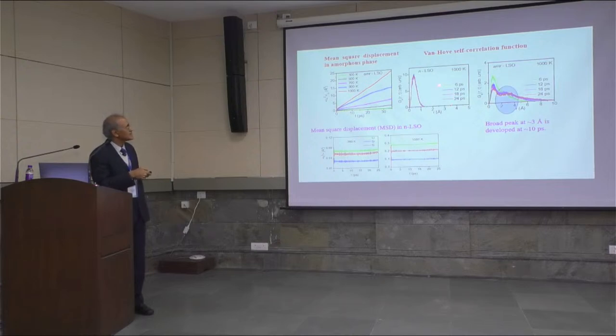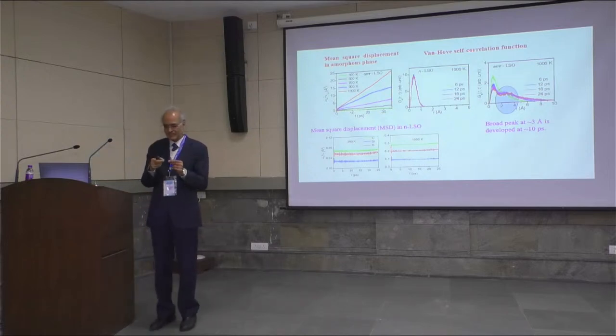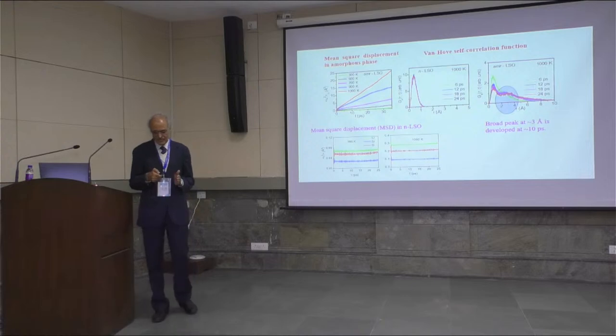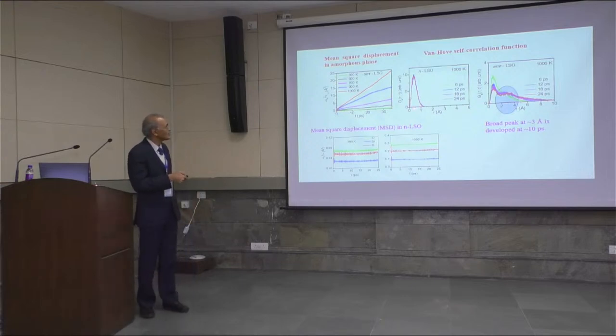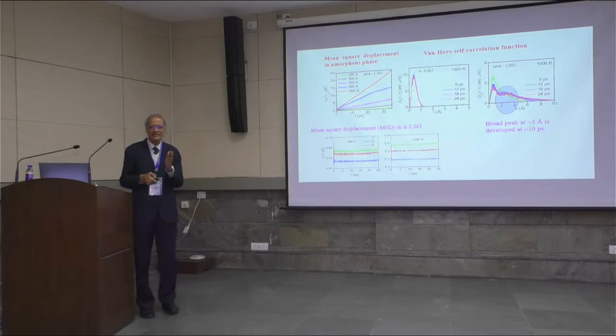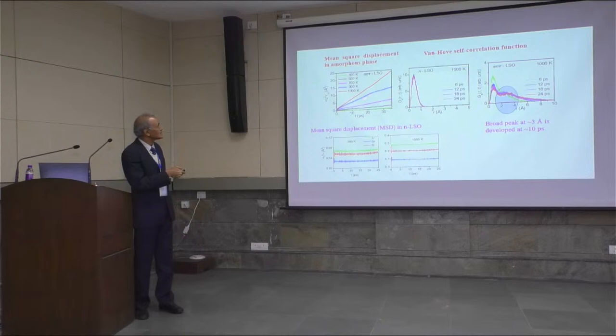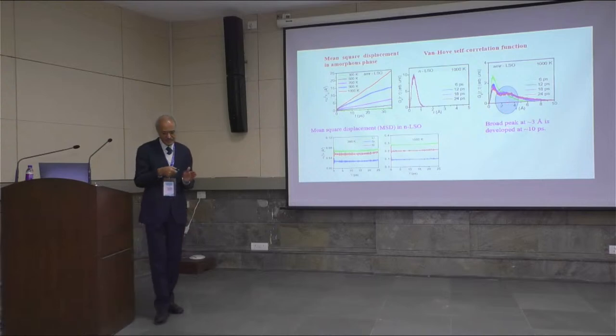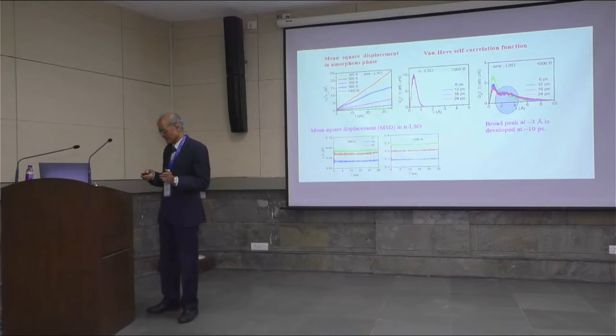Then another quantity that is calculated is what is called the self-correlation function. It's a correlation function between a lithium atom at a given time and at a future time. If you calculate that in a crystalline material, what you find is that there is just one peak, typically at, let's say, half an angstrom, and this is related to just the mean square displacement of one kind of vibration. However, in this amorphous structure where there is diffusion, the self-correlation function first develops a second peak and then further peaks and so on. So this indicates how, as a function of time, the atom is jumping from the initial site to another site.